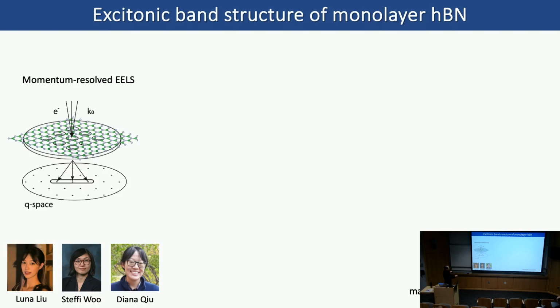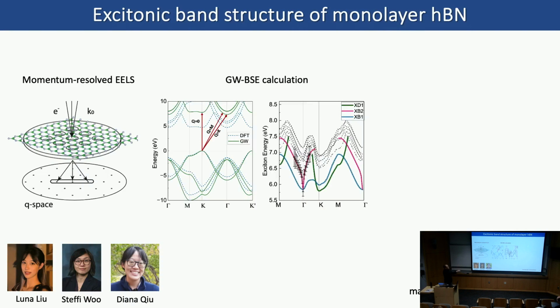I want to say this is actually in charge by my student Luna, in collaboration with Steffi from Oak Ridge and Diana from Yale. So this is a GW-BSE calculation of the monolayer hBN. Basically, it shows that for the GW calculation, the electronic band structure still shows a perfect indirect bandgap configuration. So from this point to that point actually forms the lowest energy difference.